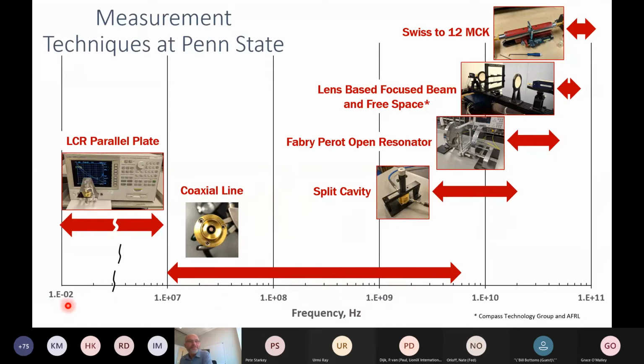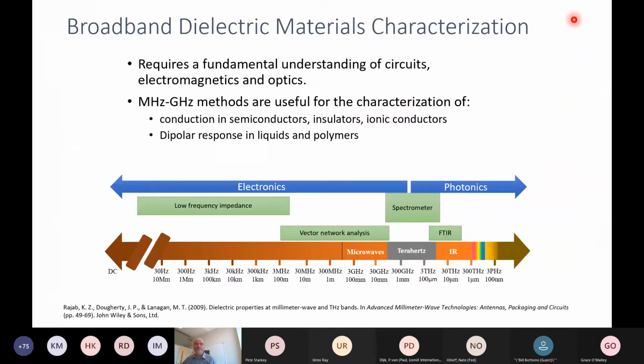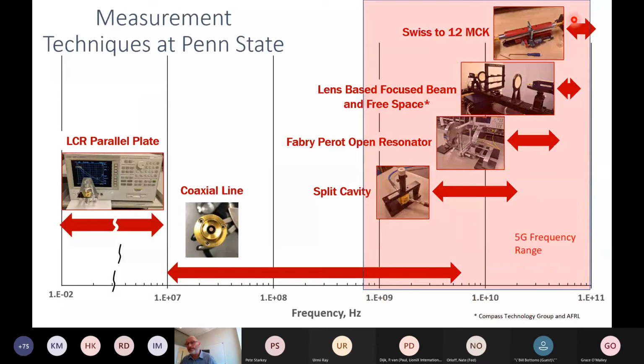So the first 9 orders of magnitude can be accomplished by a simple parallel plate method. We do adapt that a little bit to this terminated coaxial line, where we have a small sample basically on the end of a coaxial line, and then we have a large number of measurements that are available between 1 gigahertz and 100 gigahertz, for example. So I'll be focusing mainly on the high frequency for this 5G presentation.